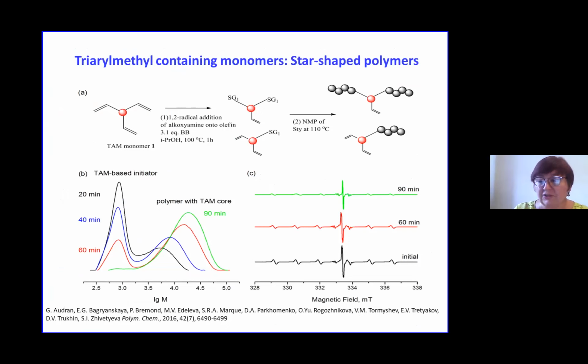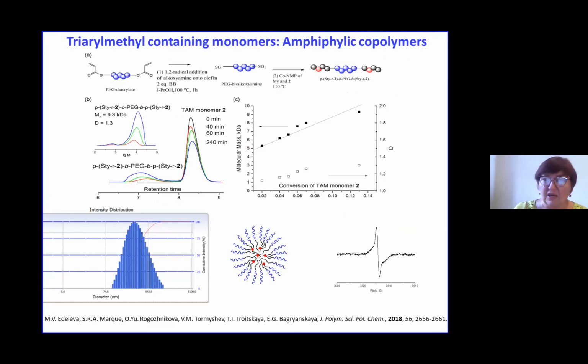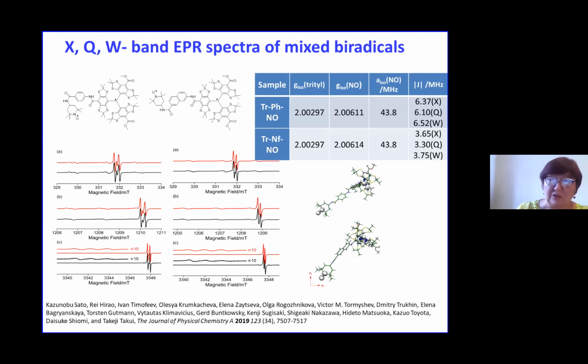One can also attach trityl to a polymer and make it so stable that it allows one to make NMP when it's present in the polymerizing solution. So the idea here was to put trityls here, and here are micelles, and then look into the EPR signal. One can get information about the disappearance of this. This was already shown in Sato's presentation.